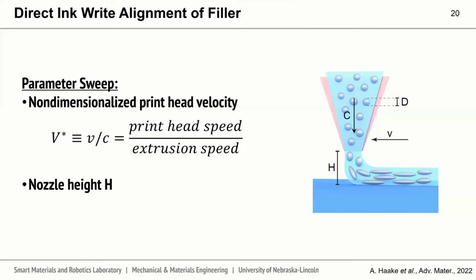For this, we did a parameter sweep, looking at two specific parameters: the non-dimensionalized printhead velocity, which is the ratio of printhead speed to extrusion speed, and the nozzle height with respect to the print bed.